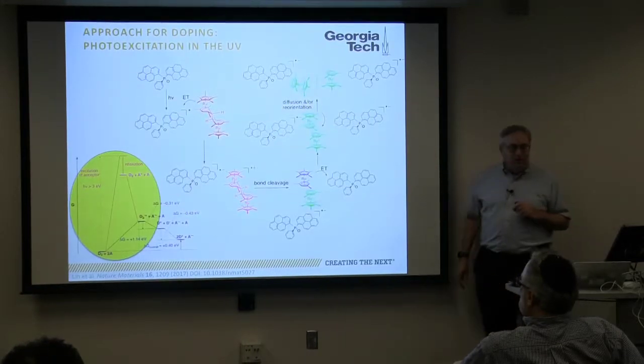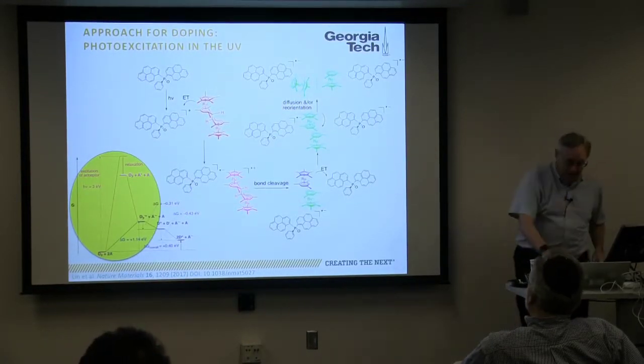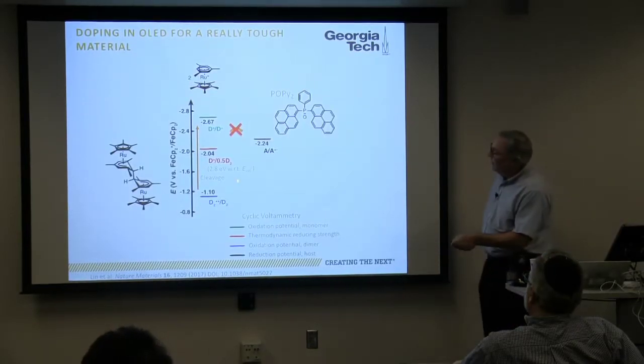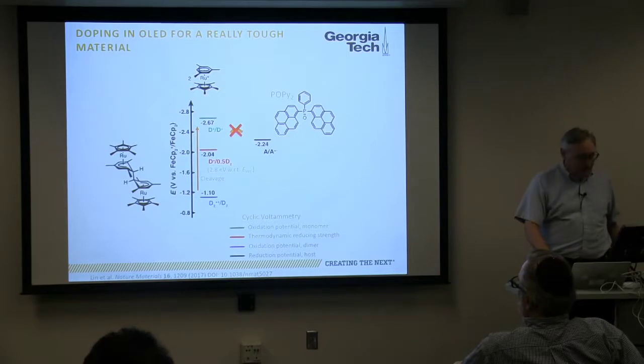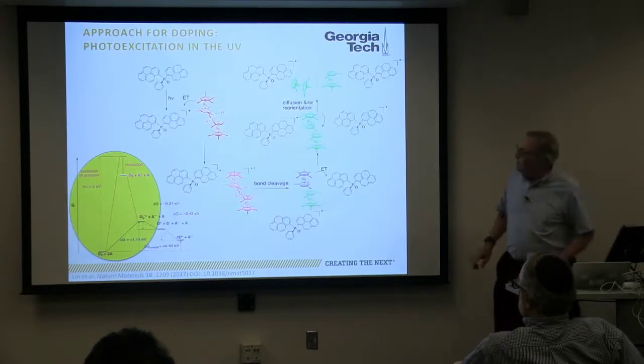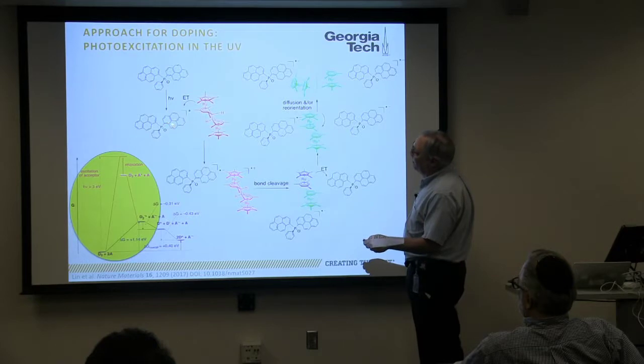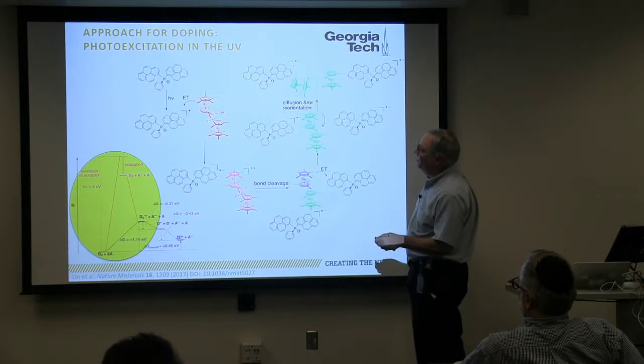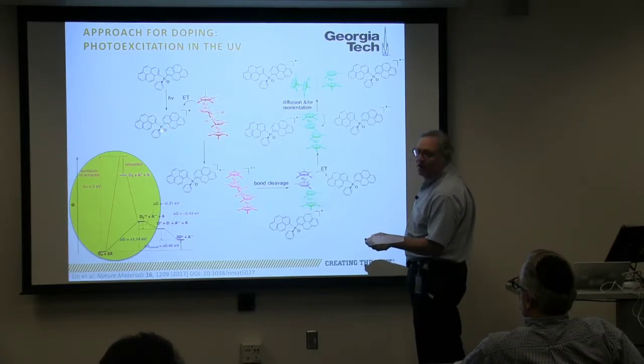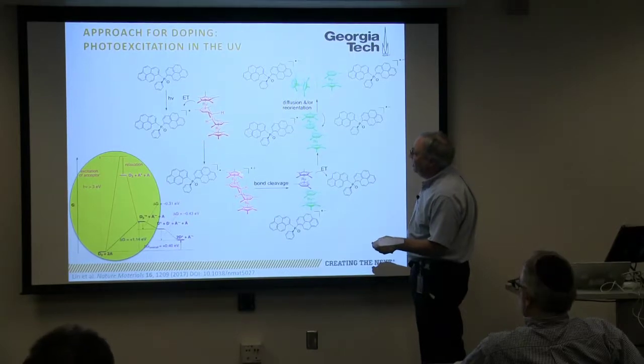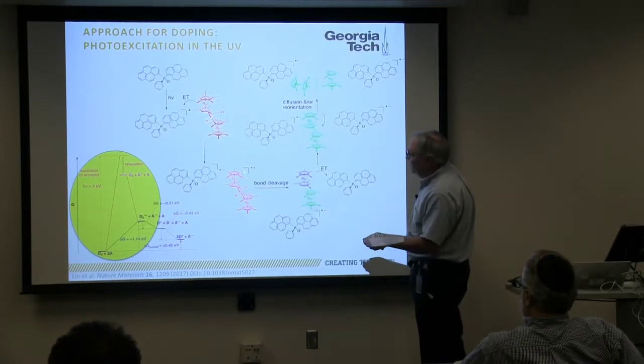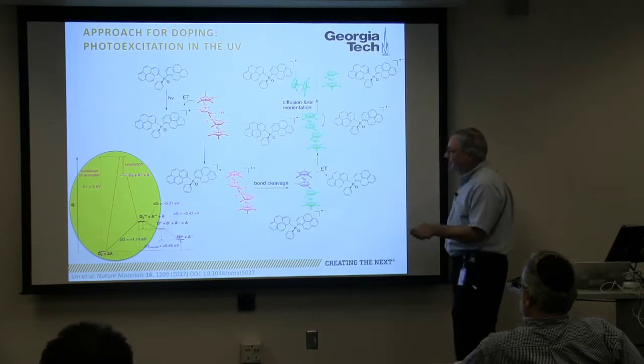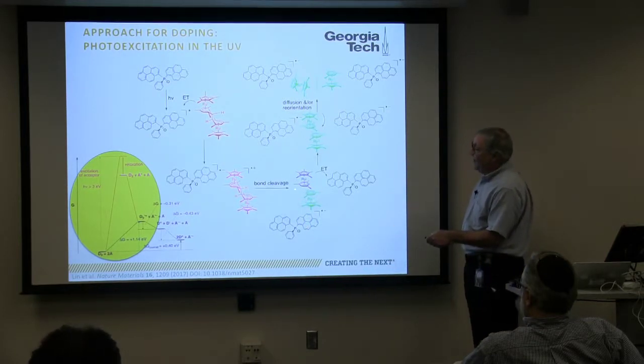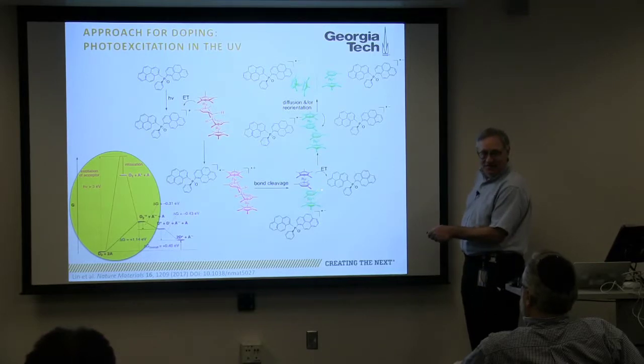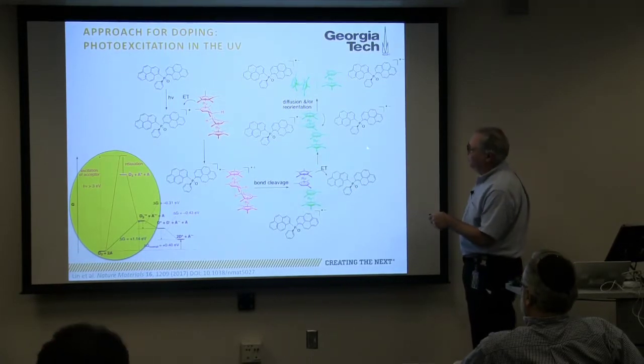And since we couldn't do it thermally because it was so uphill, we got around it using a technique called photoinduced electron transfer. In that technique, we take this molecule and photoexcite it. That puts one electron from the HOMO into the LUMO, in a very simple picture. And now this can dump an electron into the half-filled HOMO, and now we have it doped. As soon as we have it doped, we make that cation. It falls apart to give one cation, one anion. And now we do have, transiently, this very reducing material which dopes another system.